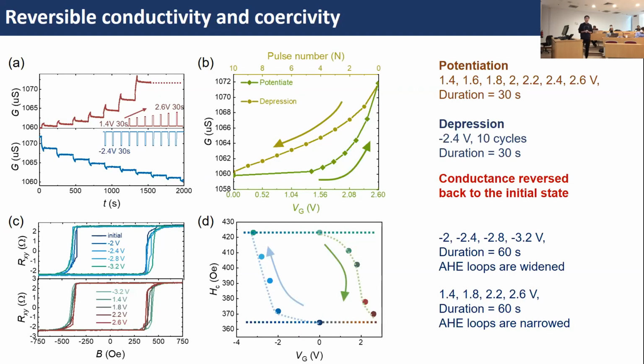And the most important thing is that for a synaptic transistor, we want the resistance, the conductance and the coercivity to be reversible. Here we apply a train of positive gate voltages and then a train of negative gate voltages to make the conductance go to the high state and then back to the lowest state. It means that the conductivity of this device is reversible. And it is the same for the coercivity. By applying negative gate voltages, it goes to the higher coercivity state, and then we can bring it back by applying a series of positive gate voltages and return the Hall effect loop to the original state.